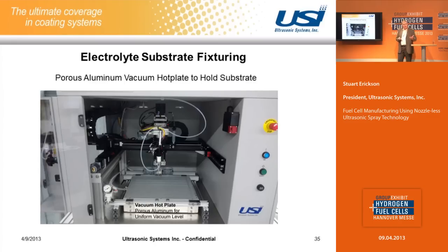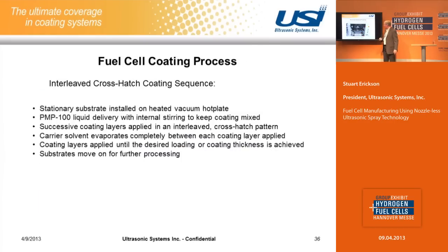Another aspect is to keep the substrate fixtured properly, and for that we have a heated, porous vacuum plate. So the substrate can be put in place and held so it doesn't potato chip or bubble. Typically what we use is that crosshatch method to build the required coating density on the membrane.